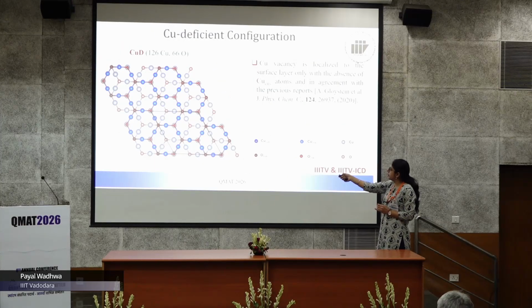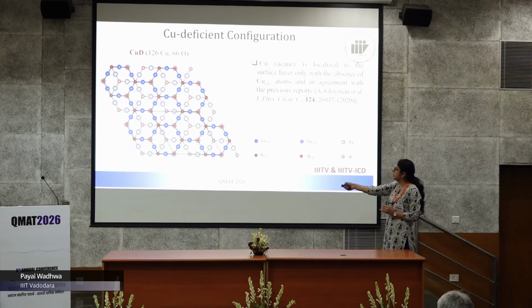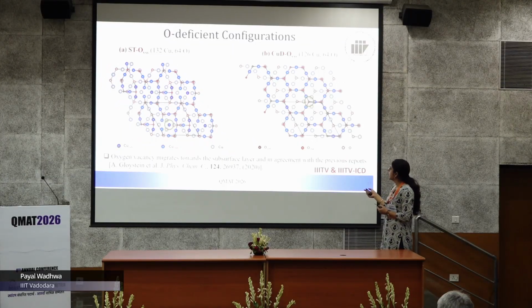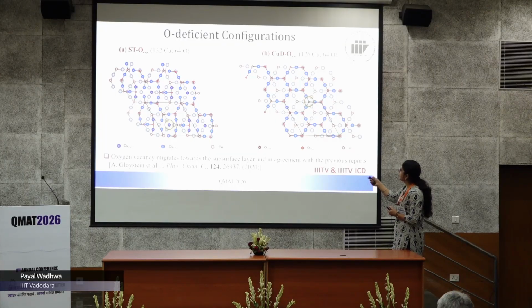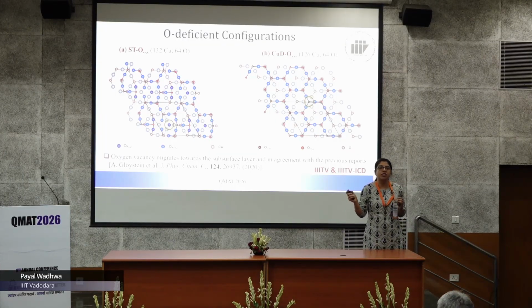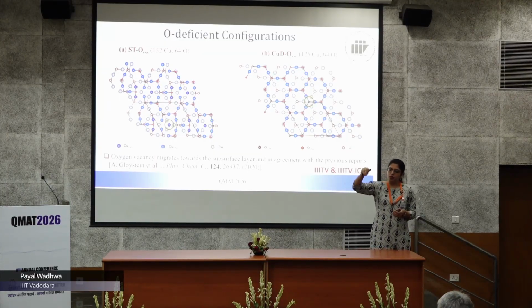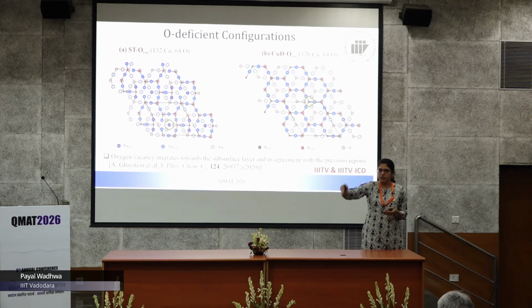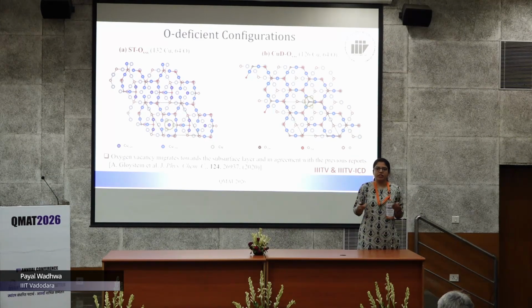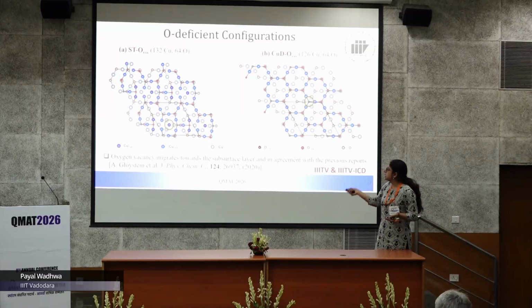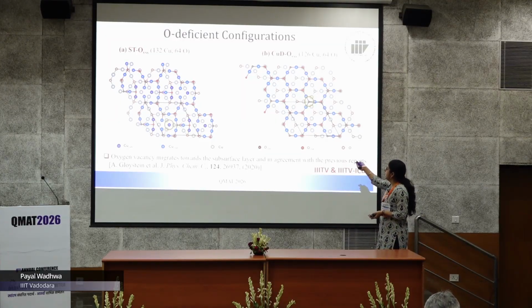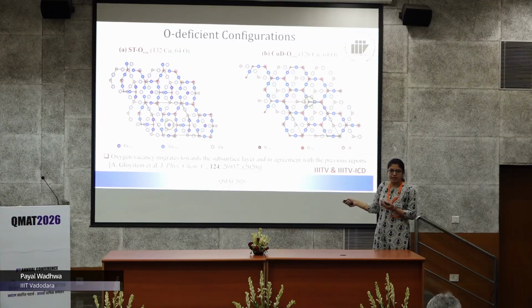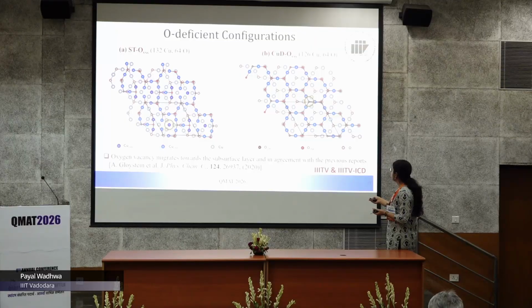When we performed it on this copper deficient configuration, we found that unstable coppers are getting eliminated, and this was also in agreement with the previous observations. Then we performed it for oxygen deficient, and we found that oxygen was getting eliminated from the subsurface layers. In DFT, we would perform it for a vacancy from the first layer, from the second layer, from the third layer, and whichever has the lowest energy would be the most stable one, right? But with the machine learned force fields, it automatically leads to the structure where the vacancy is in the subsurface layer. And this is also in agreement with the previous reports.